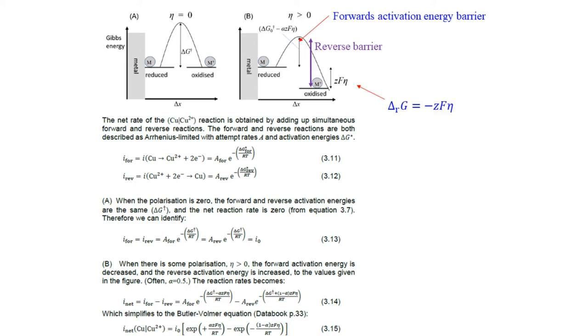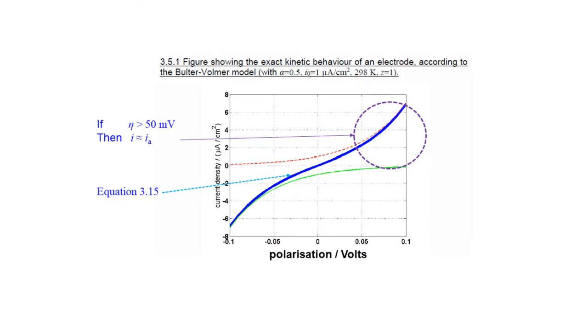It's called the Butler-Volmer equation, and it involves the exchange current density, which came from equation 3.13, and it involves two exponential terms to do with activation energy. On page 30, diagram 3.5.1 is a plot showing the current density predicted by the Butler-Volmer equation, equation 3.15, for a reaction with some typical parameters. So you can imagine this. Maybe this is a reasonable description, at least in principle, of the copper to copper 2 plus dissolution reaction.